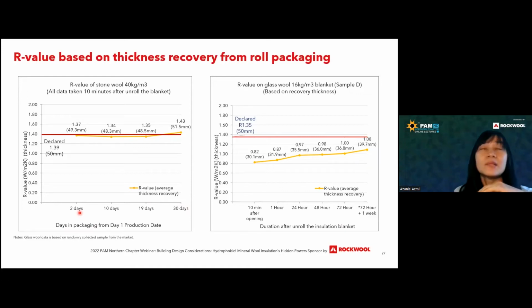The thickness actually follows the specification requirement. Under Malaysia, we follow the MS1020. For the blanket that is very long, we measure at a few places and take the average thickness. So here you see the 2 days. This data is also another thing that I want to highlight: this data is taken 10 minutes after unroll. So after 2 days, 10 minutes unroll, you measure the thickness, and roughly you will know what the R value will be.